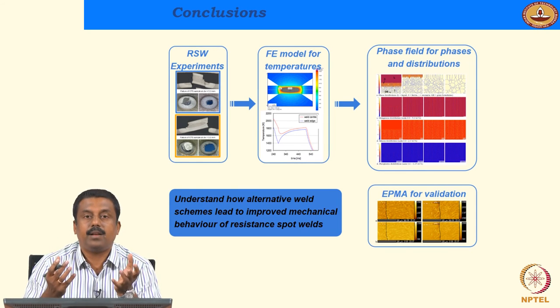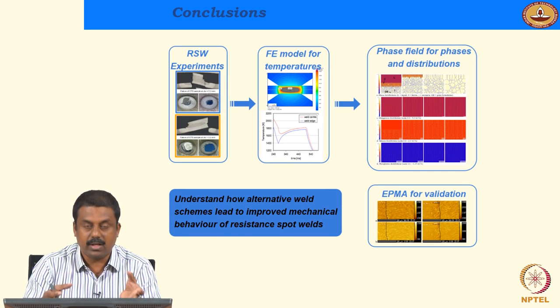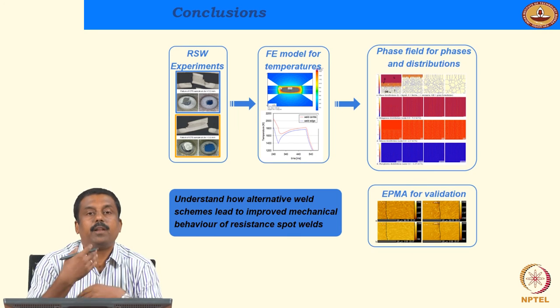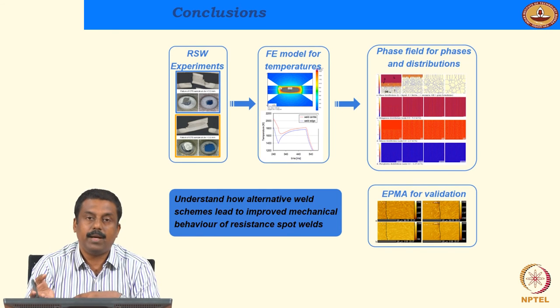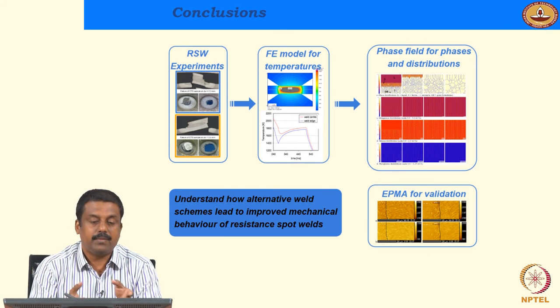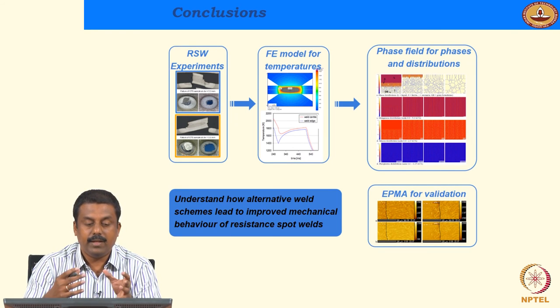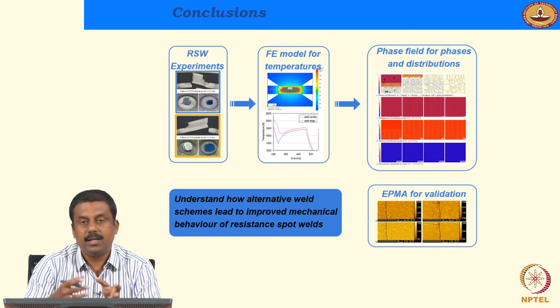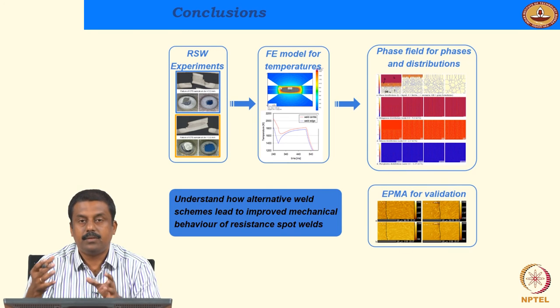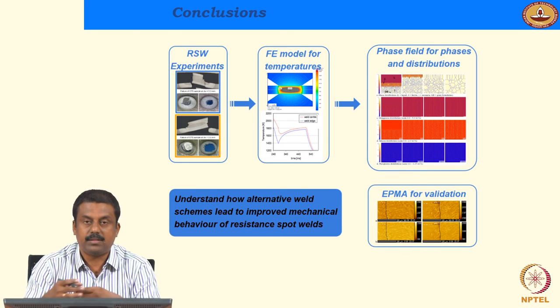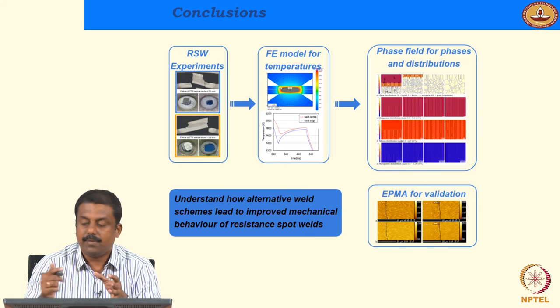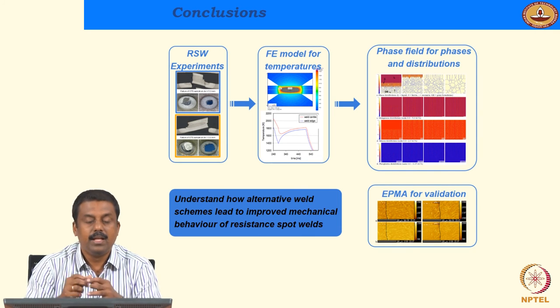And once you understand the fundamentals, what I explained in this lecture very clearly, we can improve the mechanical properties of these welds either by modifying the alloying elements or by changing the weld thermal cycle. So in this case, for example, we changed the weld thermal cycle, using double pulsing instead of single pulsing, and double pulsing leads to homogenization of the alloying elements, especially phosphorus, thereby reducing the embrittlement at the weld center line and the grain boundaries. So the lesson I want to give you from this lecture is, conventionally what we are doing